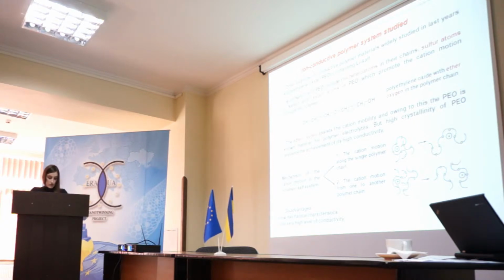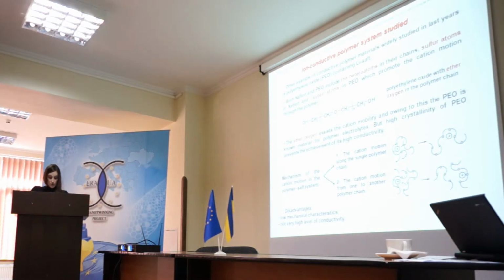Another example of conductive polymer materials widely studied in recent years is polyethylene oxide containing lithium salt. Such polymers are perspective for production of lithium storage batteries. High content of ether oxygen in the polyethylene oxide matrix is the main structural particularity that contributes to cation motion and transfer along the single polymer chain or from one chain to another. So, if you want to obtain ion conductive polymers, you should first synthesize materials with such a specific structural feature.